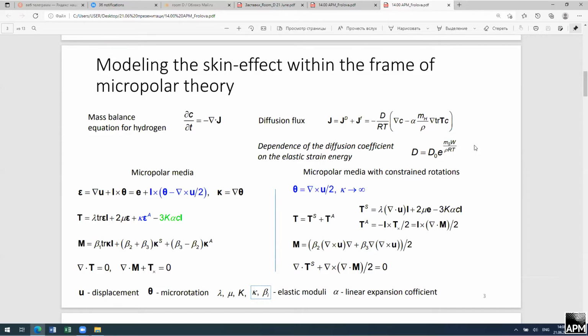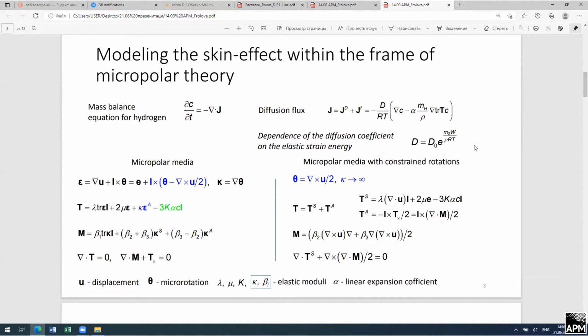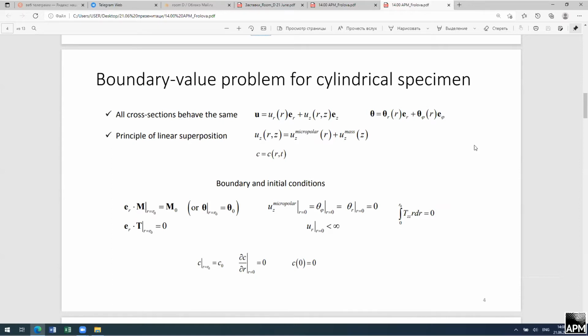In particular, we consider a specific case of micropolar media, namely micropolar media with constrained rotation, where independent rotations are absent and the non-classical elastic modulus kappa goes to infinity. In this case, it is necessary to find the antisymmetric part of the stress tensor directly from the balance equation, not from constitutive equations. We solve a boundary value problem for a long cylindrical sample to model the real experimental data that we have. And here we take into account axial symmetry, assume that all cross sections behave the same, and also use the principle of linear superposition while talking about axial displacement. So we consider axial displacement as a sum of two terms. The first term is due to the micropolar solution, and the second term is due to non-homogeneous distribution of hydrogen.